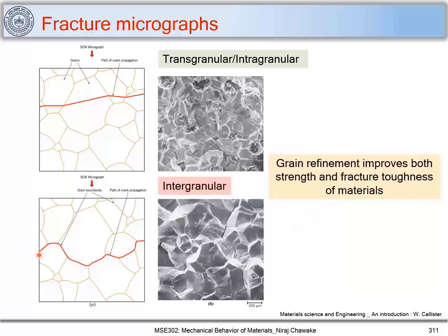So as you can see, if I have finer grains, the crack will take a longer path along grain boundaries, and thus grain refinement improves fracture toughness, and we have also seen that grain refinement improves the strength of material. Now let's go on and try to understand how we can design a material to resist fracture. So the first thing is avoid sharp cracks.